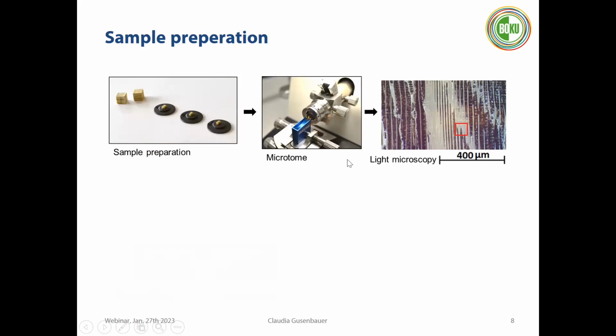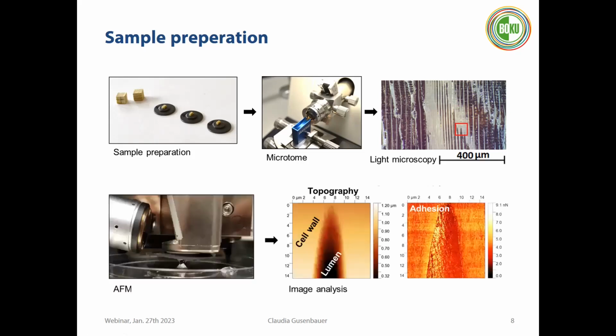And then before we perform the AFM measurements, we select suitable cellular layers with light microscopy. So as we know, wood is very variable and has a lot of artifacts. We first need to check in a light microscope if we have flat measurement positions, which we can use for AFM measurements. And then we can perform the AFM measurements with our setup. And then we get these topography images. So here I use the software Gwyddion, which is free software where you can nicely analyze your AFM data.